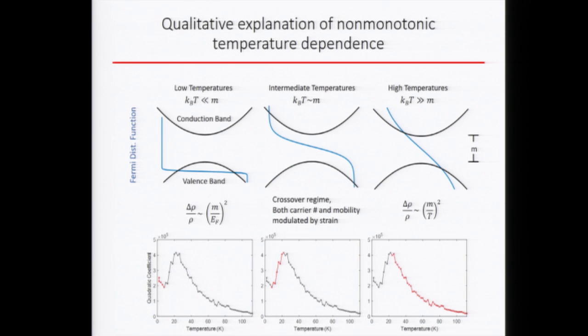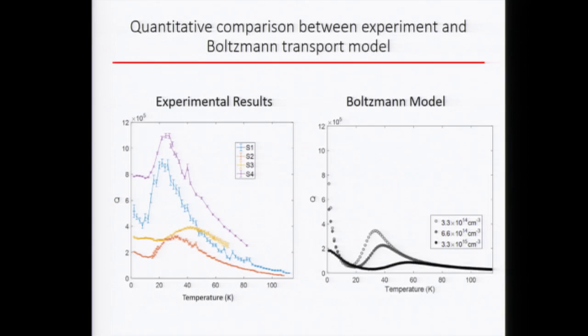And then eventually, as you go to very high temperature, you have a very broad smearing, and your temperature scale is much larger than the mass energy scale you can modulate. The system doesn't care about that anymore, and therefore you have a decrease in m/t². So we did a quick Boltzmann calculation. On the right-hand side is the calculation with different carrier densities. We see some nice qualitative agreement between the experiment and theory.